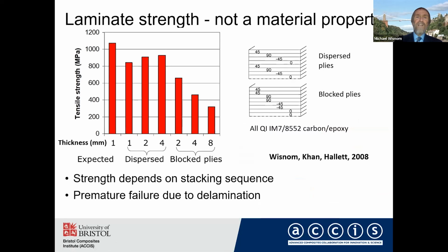So coming on to laminate strength then, laminate strength is really not a material property. So I think we have to be very careful about talking about the strength of a laminate because it depends on many factors. So the first thing here is the effect of layup. This is showing some results where we did it on quasi-isotropic IM7/8552. All these results I'm showing here on this graph are all quasi-isotropic. They're all 45/90/-45/0 layups. And the difference is in the thickness and the stacking sequence.